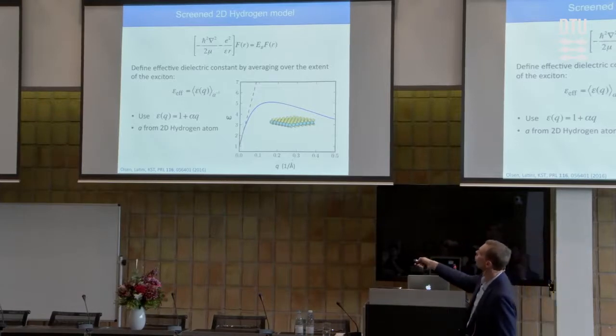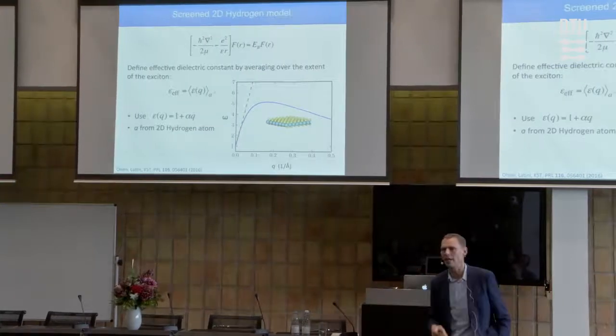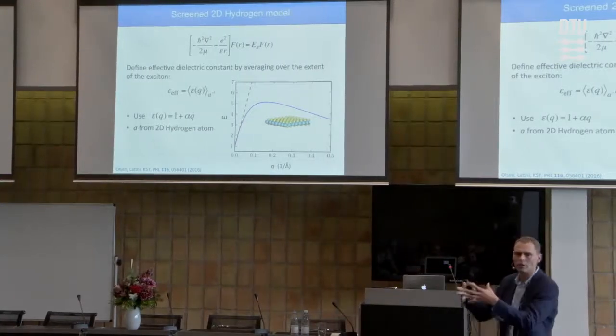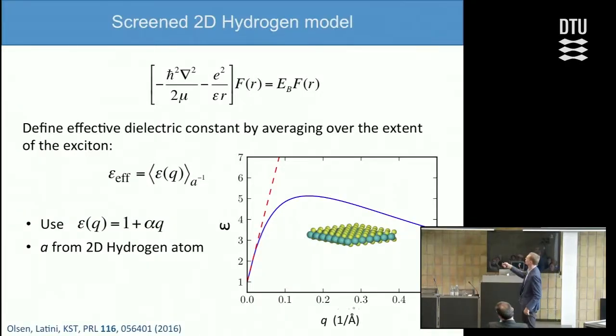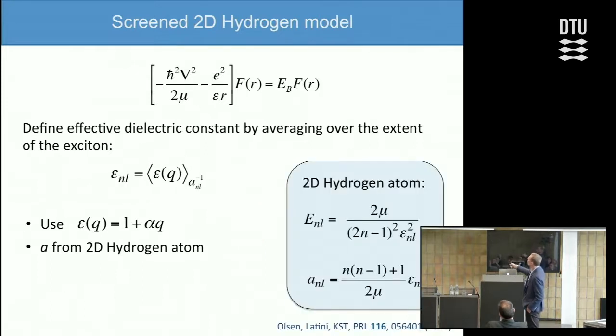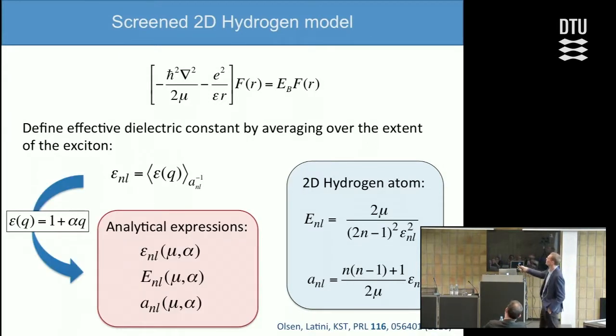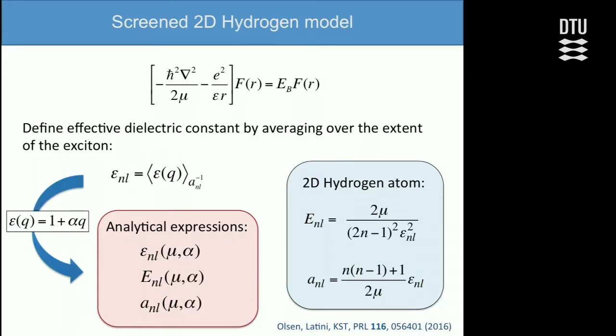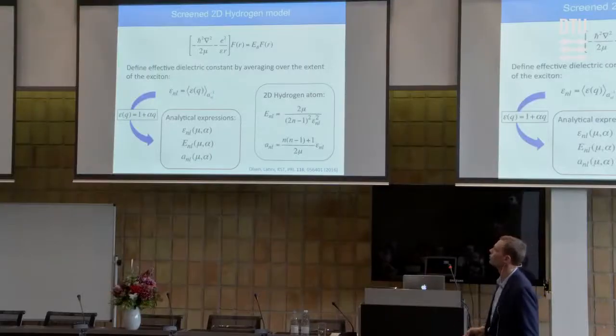That's the whole problem. So what we did, this was work together with Thomas Olsen, was instead to average the dielectric constant over the inverse radius of the exciton. That's a technicality, but it's roughly the screening wavelengths that are important for the exciton. If we combine that with the analytical expressions we have for a two-dimensional hydrogen atom, then we can end up with analytical expressions for the effective dielectric constant, state-dependent but calculated analytically, along with the energy and the radius of the excitons.